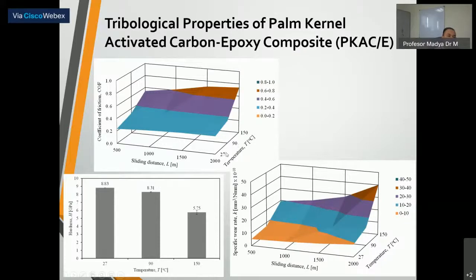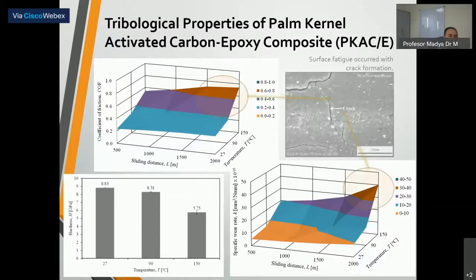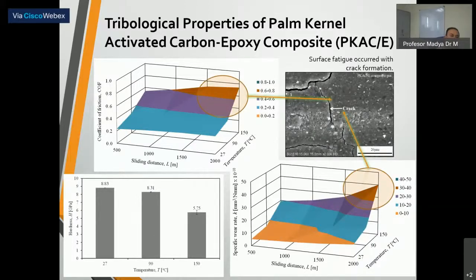We can see that at higher temperature, the coefficient of friction and also the wear rate of the palm kernel activated carbon composite increased. And we can see that the hardness also decreased with the temperature. This is most likely due to the softening of the epoxy itself at high temperature. Now at the high temperature, we can see there are some cracks at the composite surfaces.